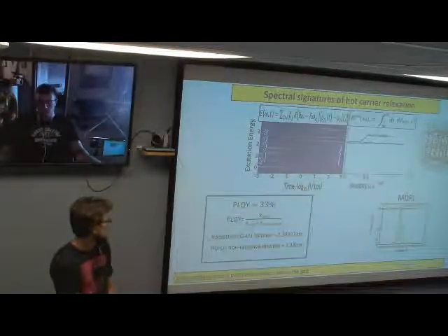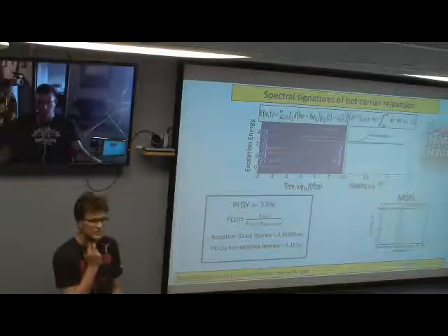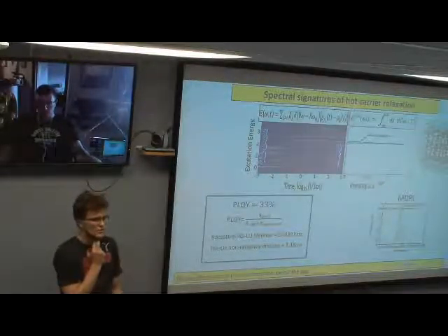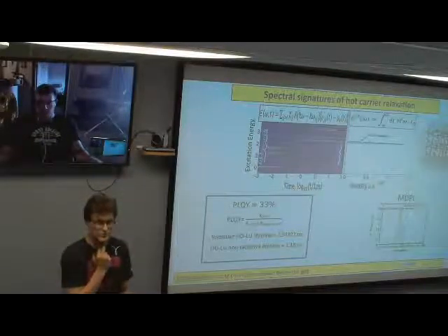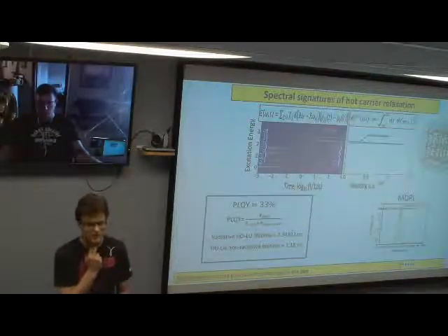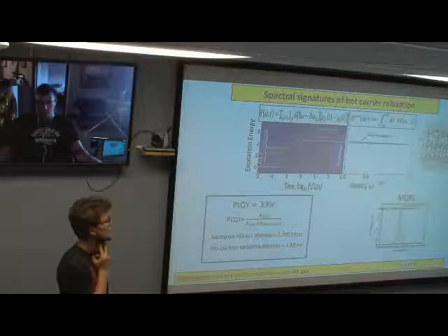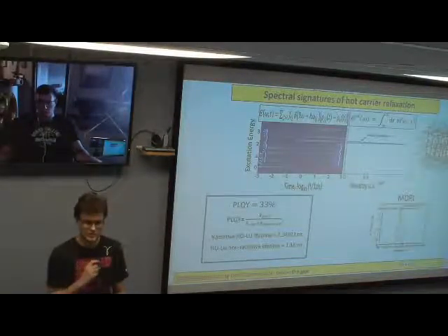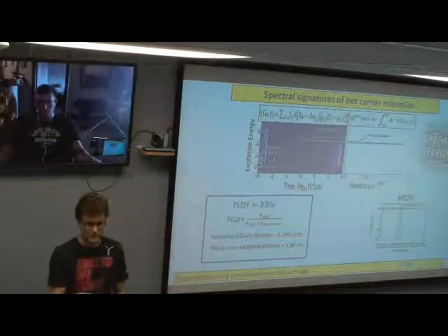And if you do the calculations, you get a photoluminescence quantum yield of around 33%, which is, well, generally low for these systems. It would be good for pretty much anything else. But usually if you have a fully passivated quantum dot, you'd expect near unity photoluminescence from these systems.